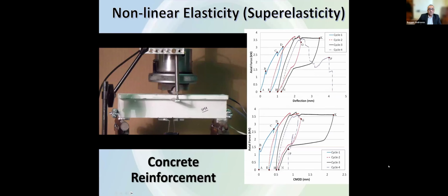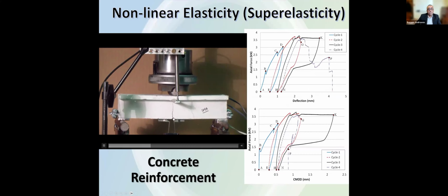Going back to the superelasticity, for those who are not sure about the self-centering capability, what does this mean? This is a simple beam. We're subjecting it to bending. It has two SMA superelastic bars inside. Look at the crack forming in the middle. Well, that's expected, of course. But wait until you see when we remove the load, because it's cyclic loading, the crack will start closing. And that's what we mean by self-centering. The beam is actually having the ability to recover back to and bounce to its original shape.